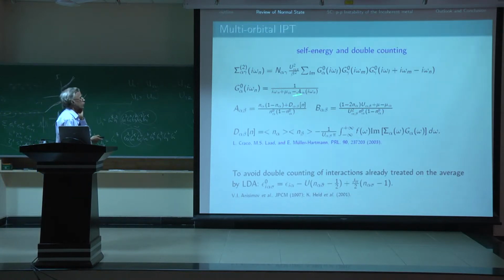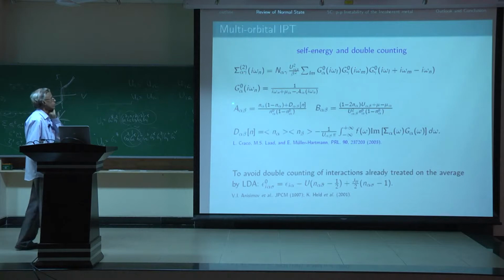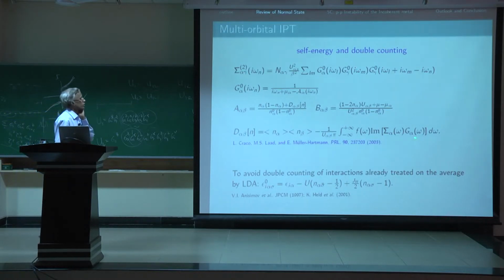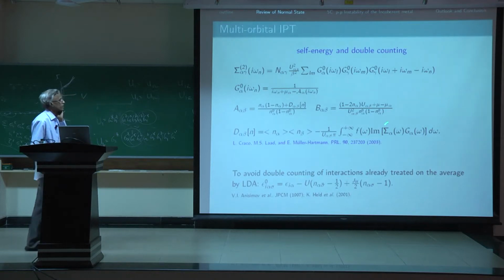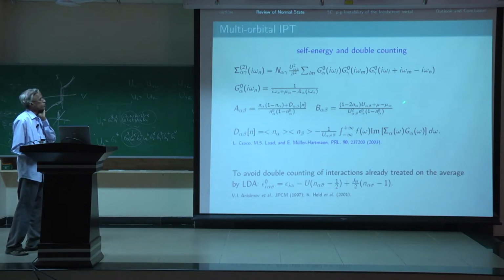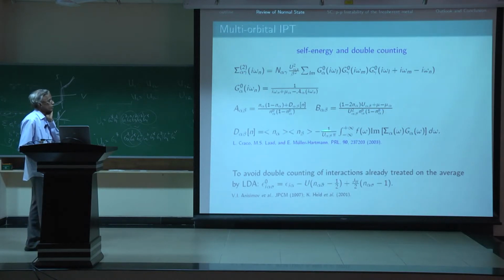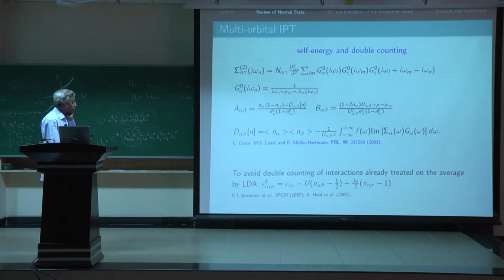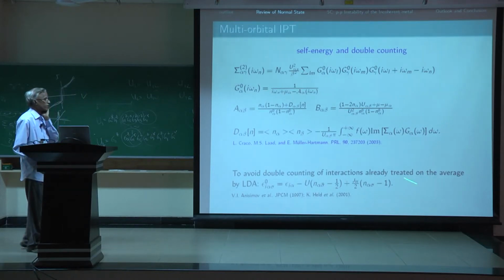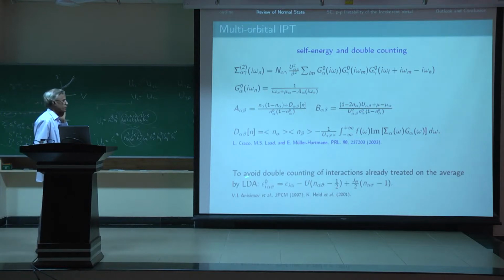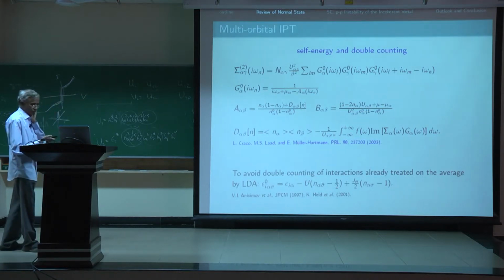So for multi-orbital systems, there are local multi-orbital correlations which are basically encoded in a local two-particle interorbital average, which can be self-consistently computed within the structure of the multi-orbital DMFT basically by writing down an equation of motion for the Green function, for the higher order Green function. And so this basically corrects earlier attempts which basically used an artificial decoupling to treat these multi-orbital correlations within multi-orbital DMFT. And in practice, one also has to avoid double counting of interactions which are already treated on the average by LDA, so there's a prescription for doing that, which is the one we used.